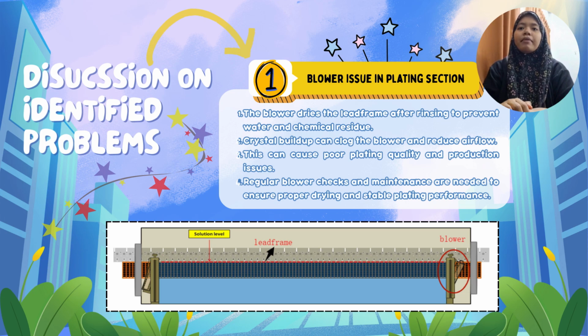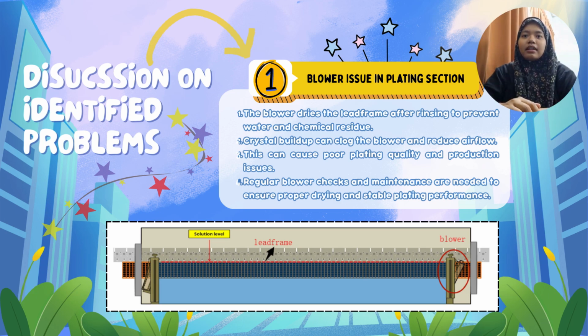For example, one major issue identified is the blower in the plating section. So this blower functions to remove remaining chemical solution that sticks to the lead frame after one process. And over time, crystal can build up from the electrochemical process itself and can clog the blower. As you can see in the image, the blower was placed right before the belt going to the next stage tank. If the clog is not removed fully, it can reduce airflow and cause improper drying. So that's why contamination can occur, because chemical from another tank can drip or fall into another tank.